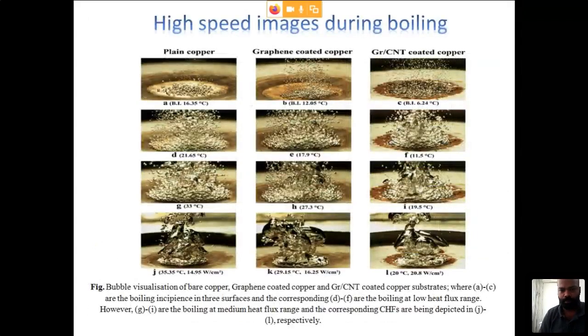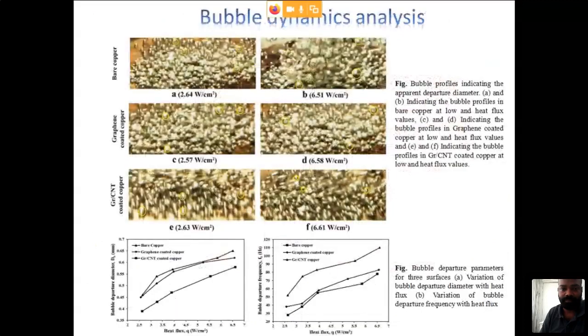This is the basic boiling dynamics. You can see the bubble dynamics here. Now it is taken with different temperature values and heat flux values for different surfaces, and you can see that in case of the graphene coated or graphene carbon nanotube coated surface, the number of bubbles is high as compared to the other two surfaces, as well as during the higher heat flux the individuality of the bubbles is maintained even at very high temperature.